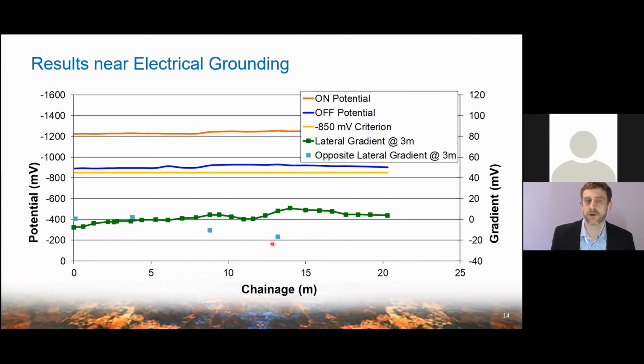And the same thing is happening here. So it appears then that instead of being a coating defect on my pipe, it was actually associated with the building that was right next to this location, and specifically the electrical grounding. So there were ground rods at these two locations. So it was very satisfying to be able to go in the field and say, okay, there are actually ground rods here, and therefore I'm confident that these two don't represent, at least not by themselves, coating defects on my pipeline. And I'm also happy to see that my protection levels indicate I'm fully protected.